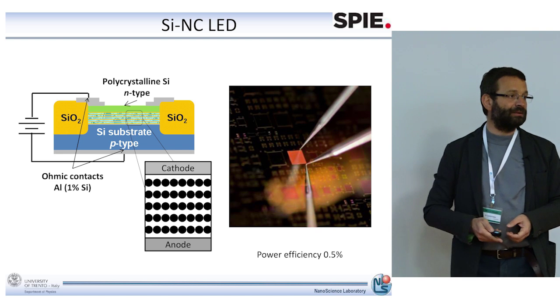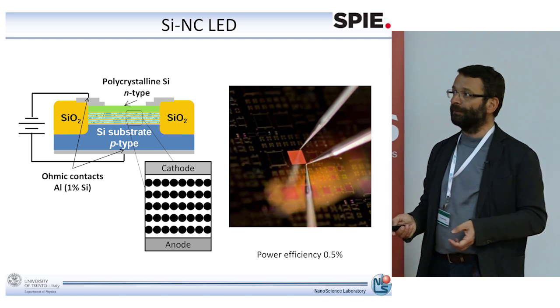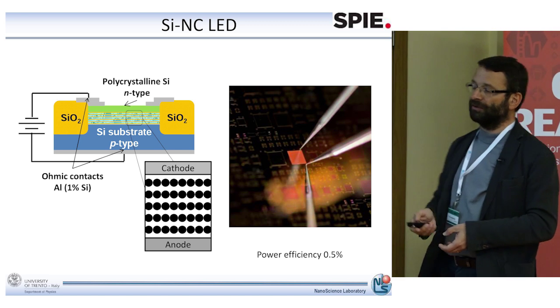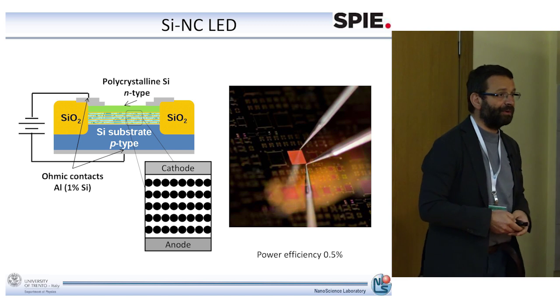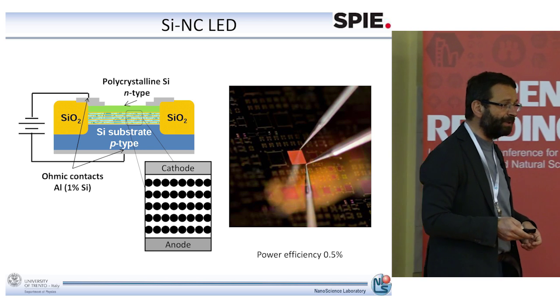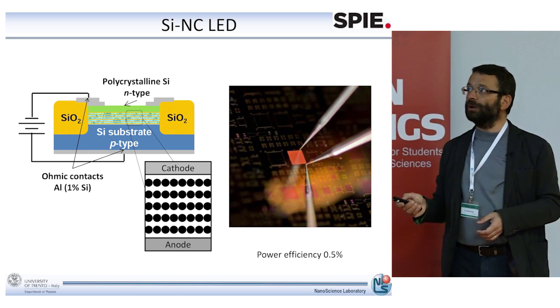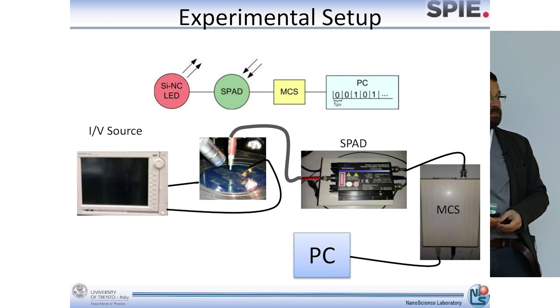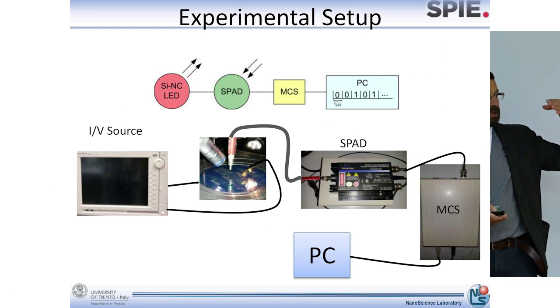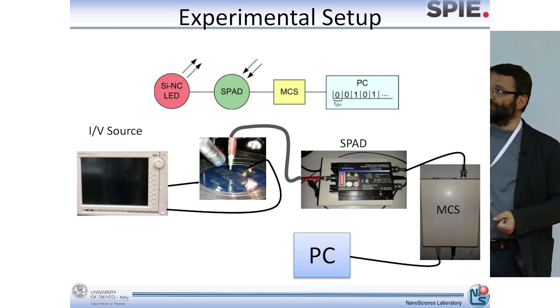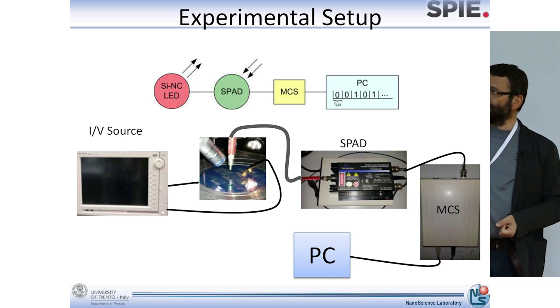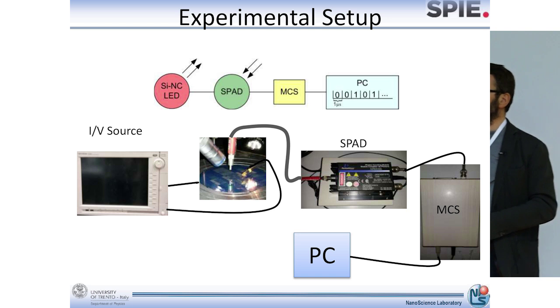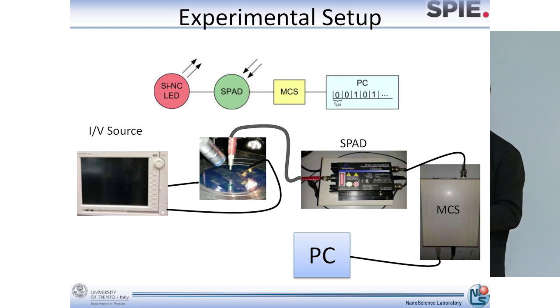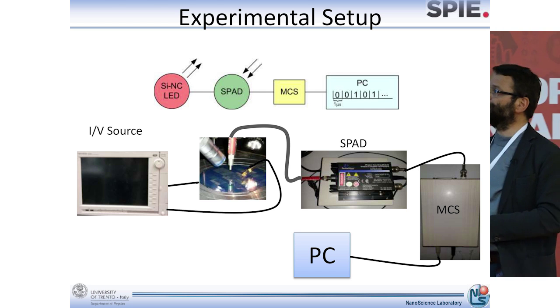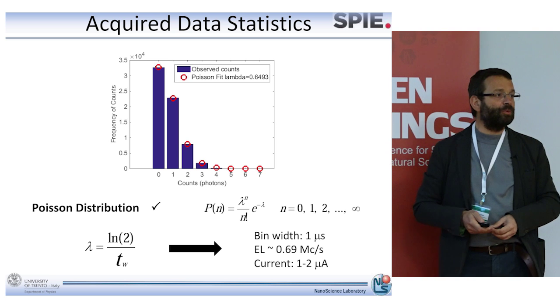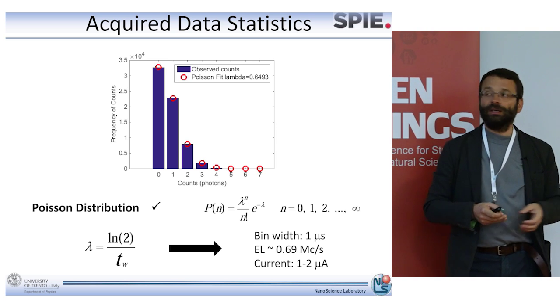And in our case, the quantum source of randomness is spontaneous emission. So this is very simple. We use our nanocrystal. And now the problem that the power efficiency is not large is no longer a problem, because what we did is simply we look at the time when the nanocrystal emits a photon. So we look at the arrival time of the photon by using a single photon counter, and then we acquire the data so that we generate the random bit stream here.